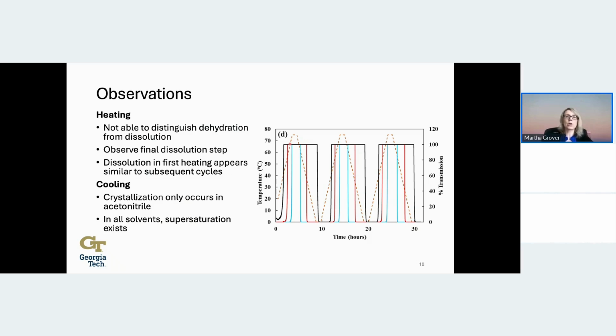We don't really know, under this sort of heating in acetonitrile, how long it would take for the water loss. Recall that when we did the slurrying in acetonitrile at ambient temperature, it took somewhere between 4 and 24 hours to lose the water. But now we're at elevated temperature, so we're just not able to say from this data when the water loss is occurring and if we have 2 steps or 1 step. But likely we have 2 steps that are occurring, and what we're observing is that final dissolution step.